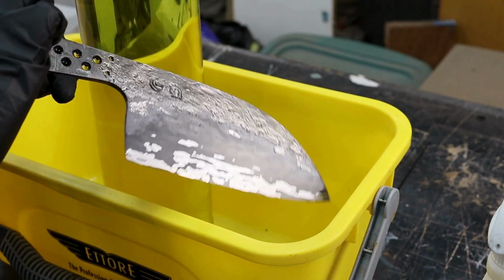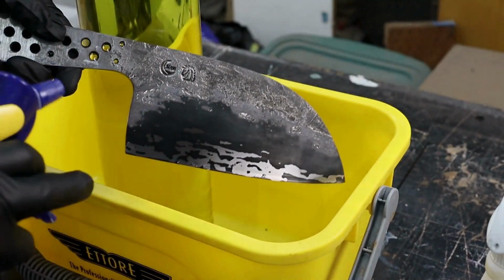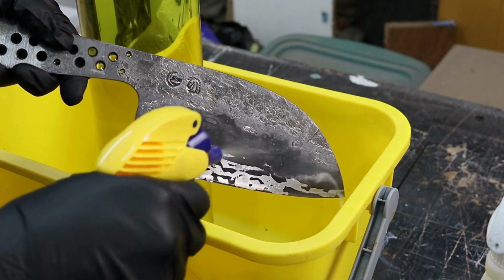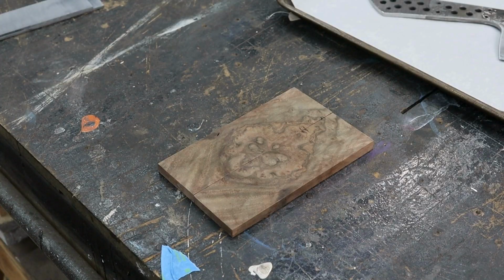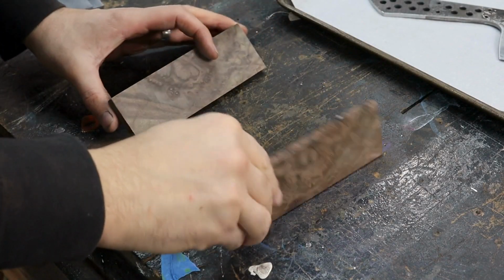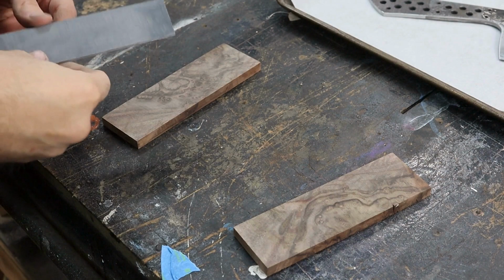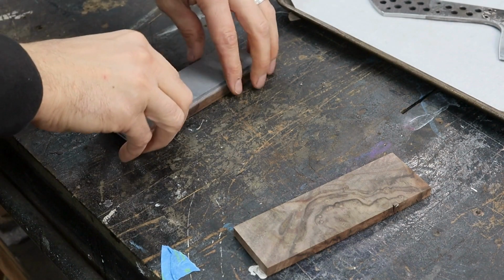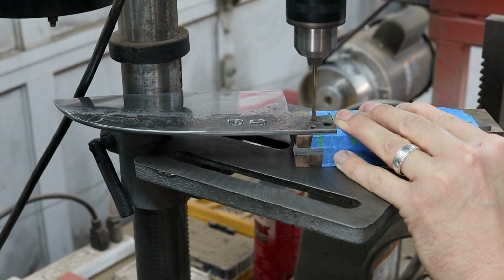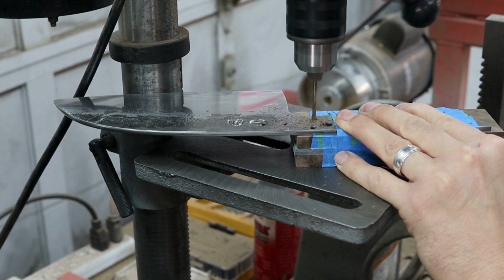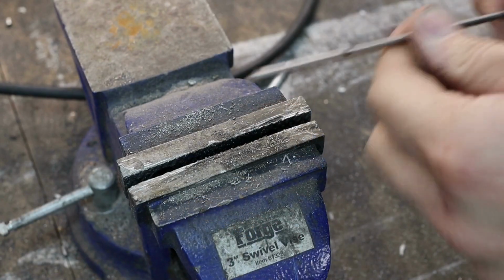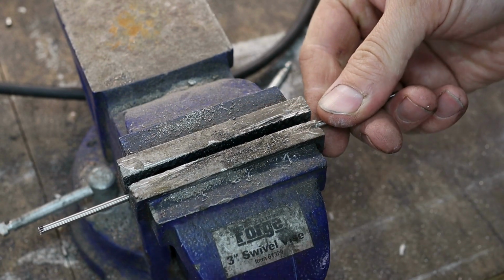You can see that the 15N20 is crazy bright right out of the acid, and the 80CRV2 is very dark. That's got me pretty excited to try out some on higher layer count knives I've got coming up. I don't think this high contrast etch is a great look for this particular knife, so I ended up sanding it with 2500 grit paper to give the 80CRV2 and the 15N20 a more subtle look on the bevels.